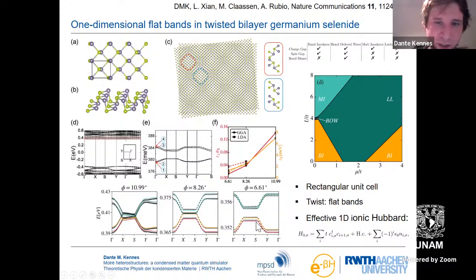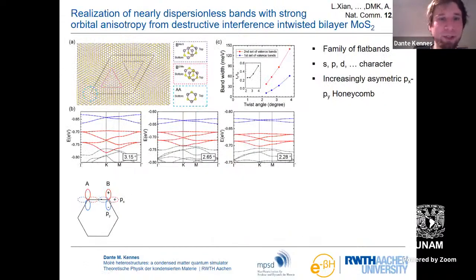Because if the interaction is weak, then obviously this kind of dispersion means you have a band insulator. Now, this fancy bond-ordered wave state, where you have a spontaneous dimerization of the bond, is actually occupying, for our numbers, only a tiny, tiny fraction of the phase diagram. And it's probably extremely hard to access. So, unfortunately, this bond-ordered wave state is probably out of the picture.